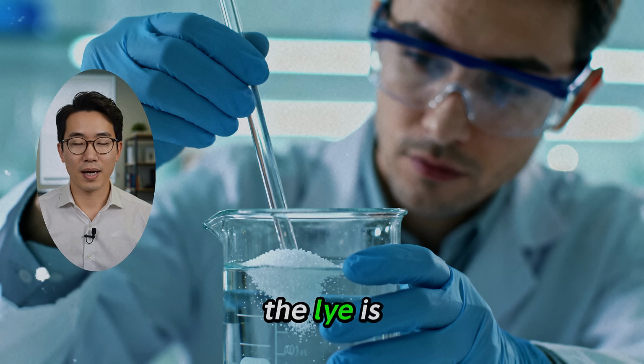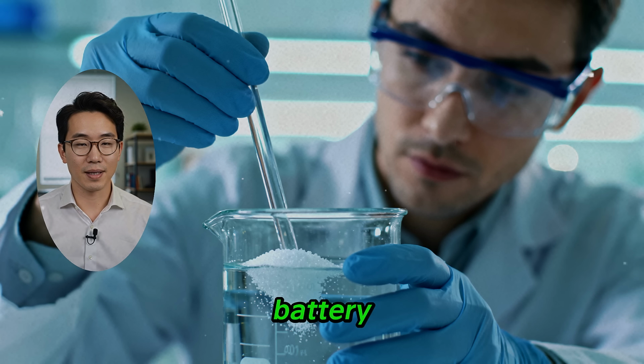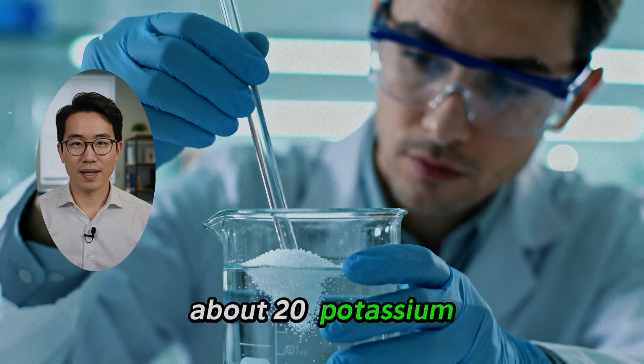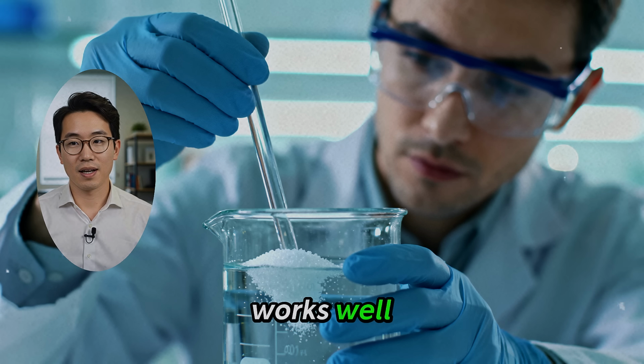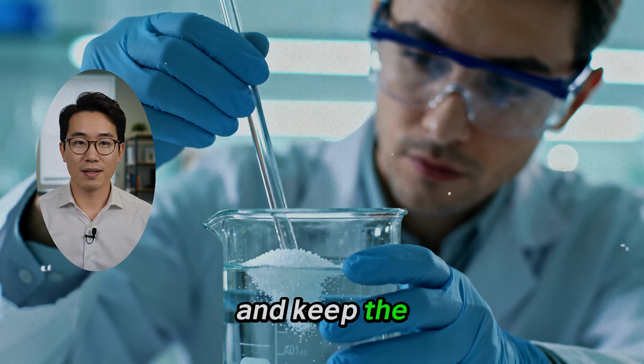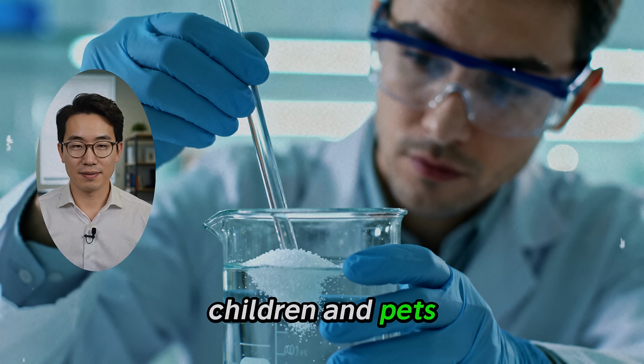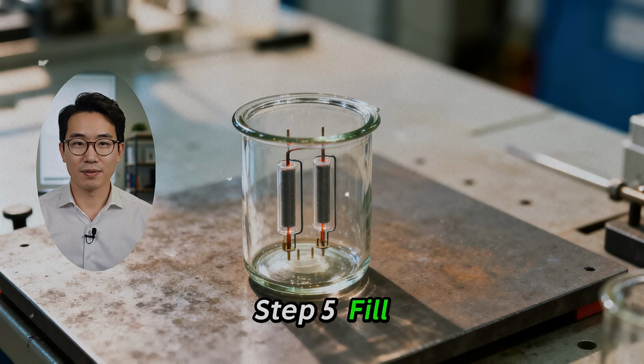Stir gently until the lye is fully dissolved. For a small battery, a solution of about 20% potassium hydroxide by weight works well. Always handle this step with care and keep the solution away from children and pets. Step 5. Fill the container.